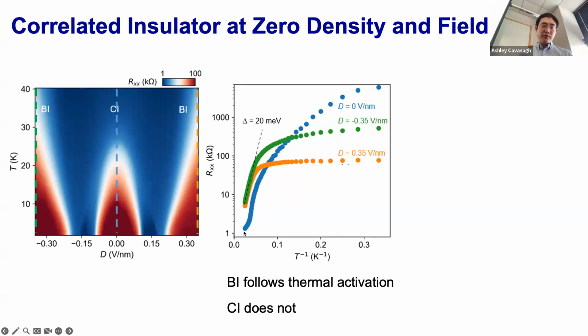And eventually at about 40 Kelvin, this correlated insulating state now becomes several times more conducting than those band insulator states. So we think what's going on here is that the band gap itself is decreasing as you warm up. So you're doping charge into a shrinking band gap, and that gives you a resistance decrease that's faster than just a single particle band being populated by temperature.